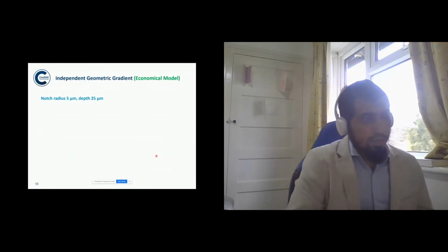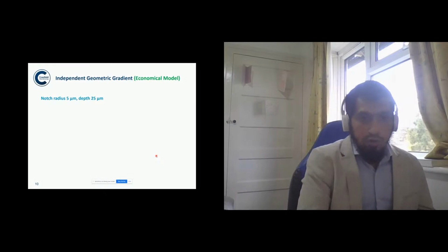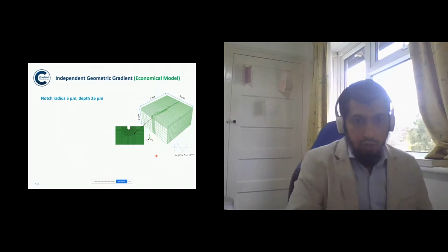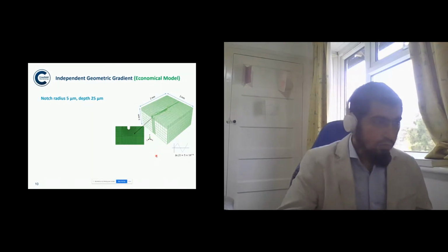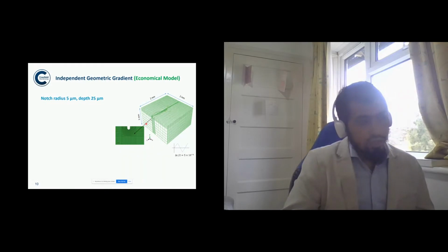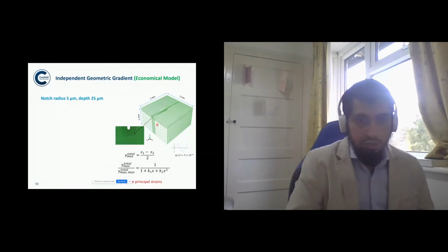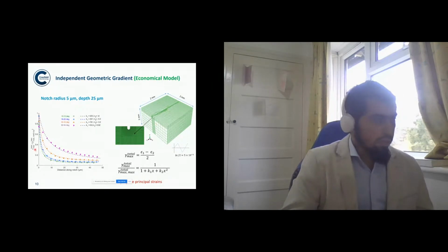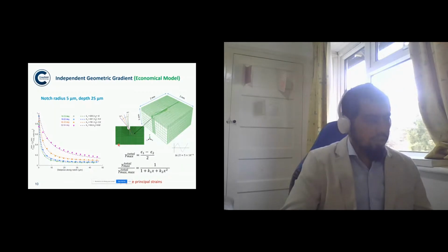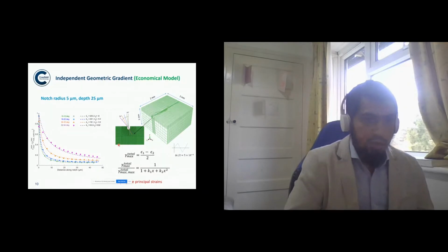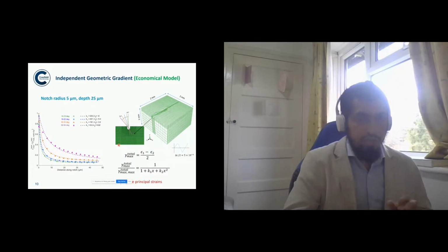So we propose an independent estimation of the geometric gradient through the homogenized model, and we created a finite element homogenized model without any microstructure, having only the notch. And we propose to capture the gradient of the notch by estimating the local shear, the maximum value of the shear strain along the radius. On this plot on the left side, we have the maximum value of the shear strain normalized by the maximum value of shear strain at the notch tip. And on the x-axis, we have the distance along the radius away from the notch. And we have calculated this maximum shear gradient at different angles along the notch. Interestingly, it gave us the same decaying trend as we have seen in the previous crystal plasticity simulation. So this is just the independent geometric gradient.